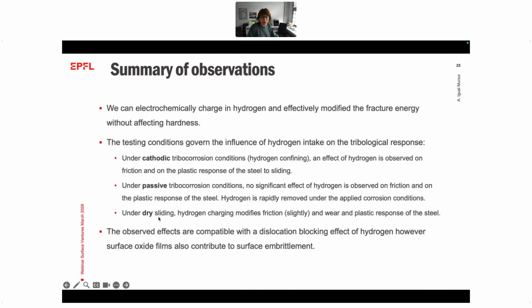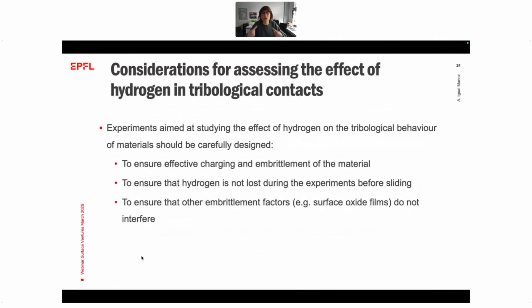And under dry conditions, again, there is a combination of the fact that we have surface films and also still the presence of hydrogen. So all these effects can still be explained with this dislocation blocking effect of hydrogen, but we have to take care about the presence of these surface films. So now we do the second iteration, the reflection from this work.